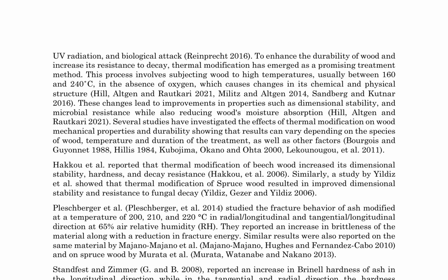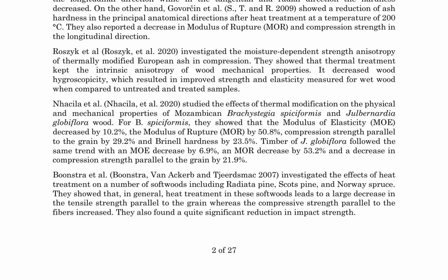For instance, thermally modified beech wood exhibits increased dimensional stability, hardness, and decay resistance, while thermally modified spruce wood shows improved dimensional stability and resistance to fungal decay. Studies have also examined the fracture behavior of thermally modified ash, revealing an increase in brittleness and a reduction in fracture energy. Similarly, investigations on ash and spruce wood have observed increased Brinell hardness in the longitudinal direction, although some studies have reported a decrease in hardness in all principal anatomical directions after heat treatment at 200 degrees Celsius.